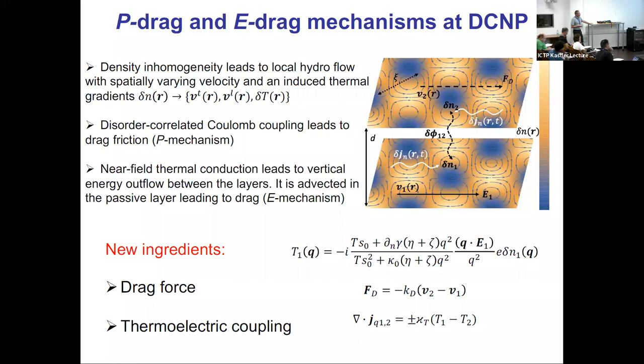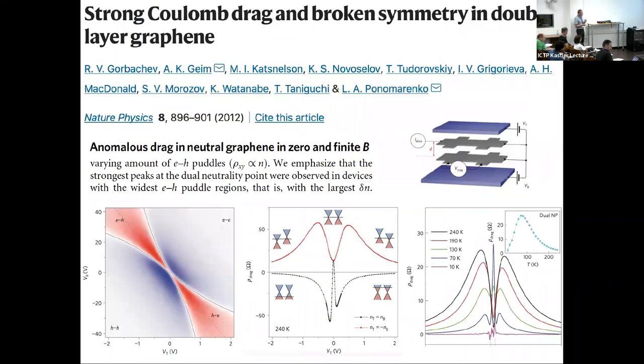complicated ingredient. We again need to recall that the system is not homogeneous. And by the way, I need to say a crucially important nuance. If you read the paper, somewhere deep in the section which says anomalous drag at neutrality, they say that we emphasize that the strongest peaks at the dual neutrality point were observed in the devices with the widest puddle regions, namely with the largest density variations. So we felt that this picture and the model that we have with this long-range disorder potential could be quite a useful model to try to address this experiment. Essentially this is what I did, just looked at two copies of these graphene devices. Because of the small spacing between them, I worked in a model where electrons in each layer see the same disorder potential, so they become disorder correlated. This becomes very important in trying to incorporate both the momentum and energy drag picture.